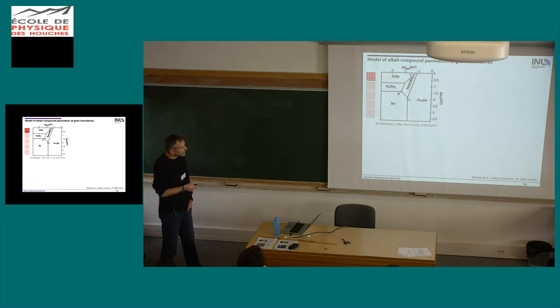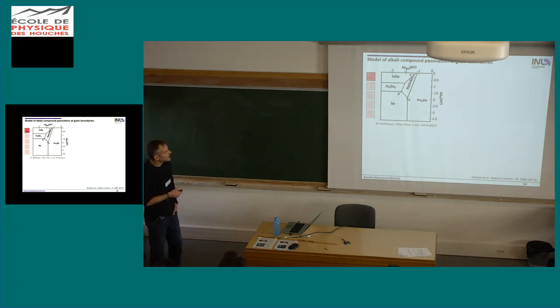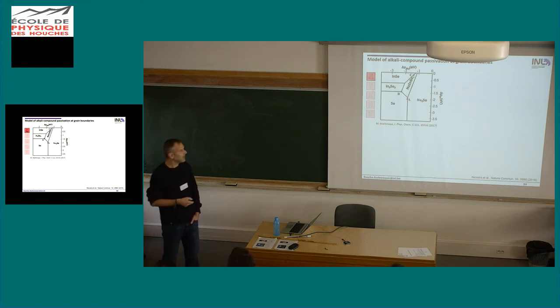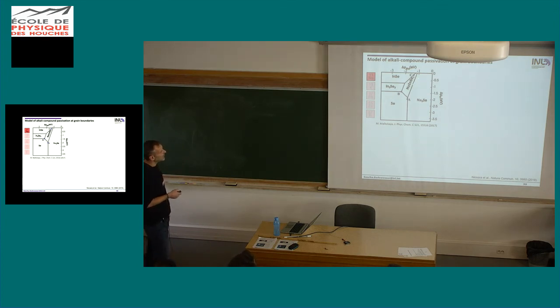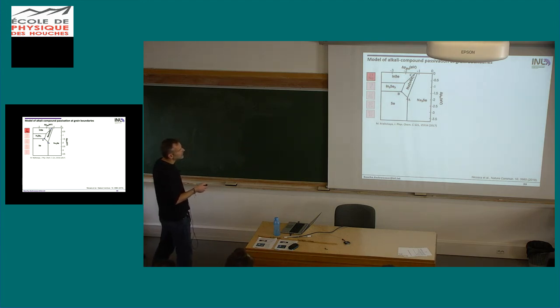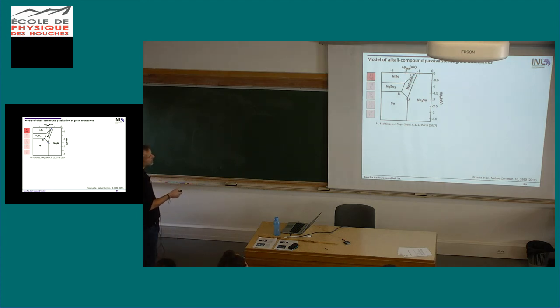So also part of this consortium was a group from Finland, from Aalto University, and they simulated by DFT simulation the stability range of alkali indium selenide material. So in the phase diagram, we also heard yesterday, phase diagrams are really messy. Here, if we look at this sodium indium selenide phase, we have the chemical potential for sodium, here for indium, and then depending on where you vary, you get sodium selenide, selenium, indium selenide, different compositions of indium selenide. But this is the one that we are interested in now. So they calculated this stability range of the sodium indium diselenide phase.